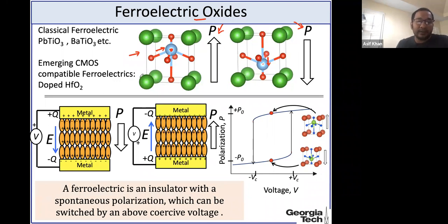moment. Now, these oxide materials are all insulators, so you can make a capacitor out of it. And if you make a capacitor out of it and measure the polarization or the charge on these metal plates as a function of voltage, what you will get is a hysteresis loop like this. Just for comparison, if this material was not a ferroelectric material, rather a dielectric or a paraelectric material, the polarization versus voltage curve would have looked something like this, a linear curve. But a ferroelectric material has hysteretic charge-voltage characteristics.